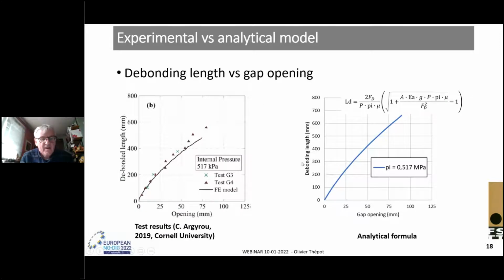Concerning the debonding length, the graph on the left shows the debonding length versus the gap opening, measured in 2 tests conducted under 0.5 megapascal internal pressure. The graph on the right shows the result of our simple analytical model. As for the tensile force, it can be seen that the formula compares very well with the test result.